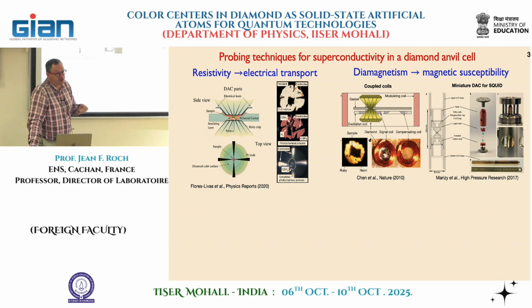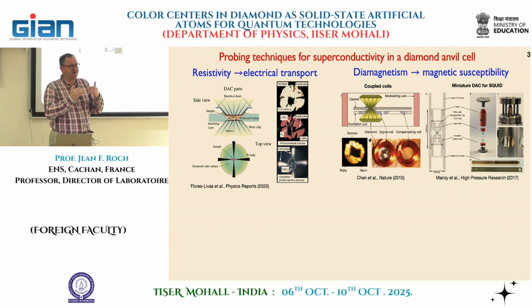Of course, what can also happen is contamination of the sample by the electrode, and this is very hard to reproduce. And somehow, making this electrode in this environment is a kind of art by itself. That's one property, and also you probe again the whole ensemble. You can have something that decreases the resistivity, but getting null resistivity is always very difficult. So this is an evidence for the existence of superconductivity, but you have to demonstrate something else. And what you have to demonstrate is the specific magnetic properties associated to a superconductor, which is a perfect diamagnetism. So you measure the magnetic susceptibility.